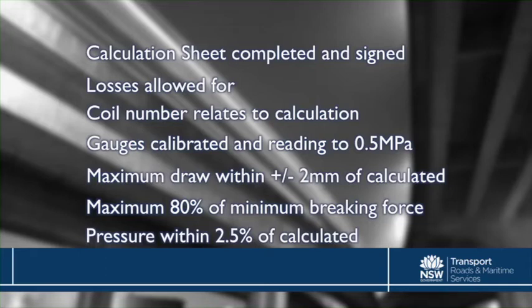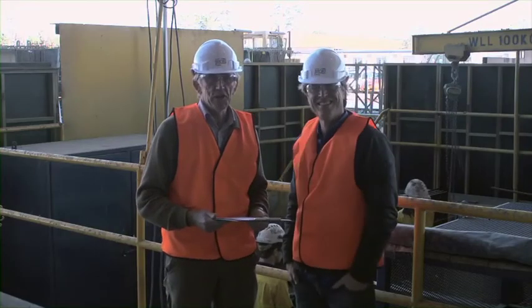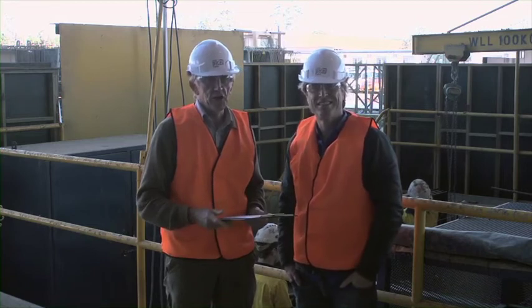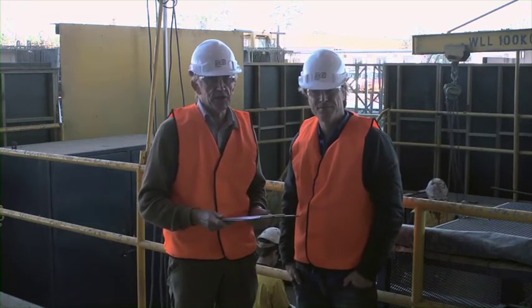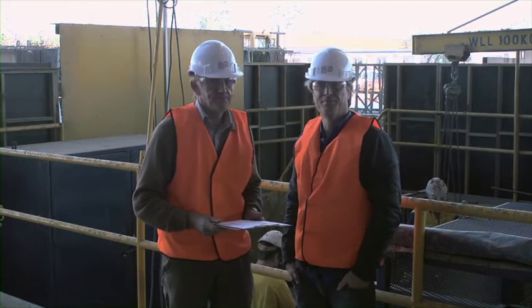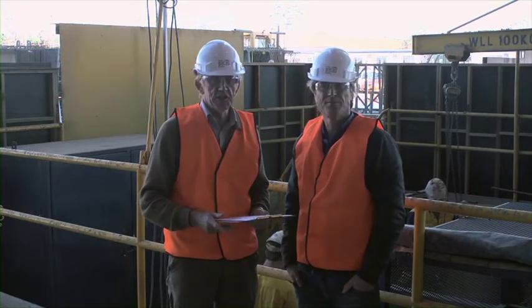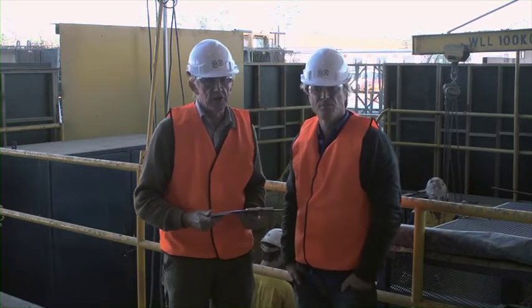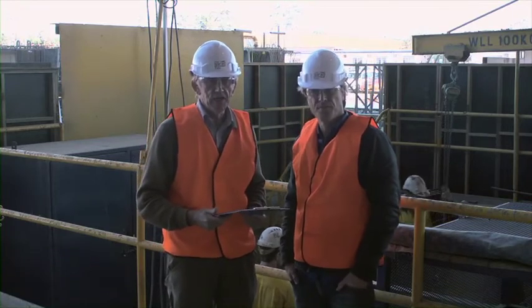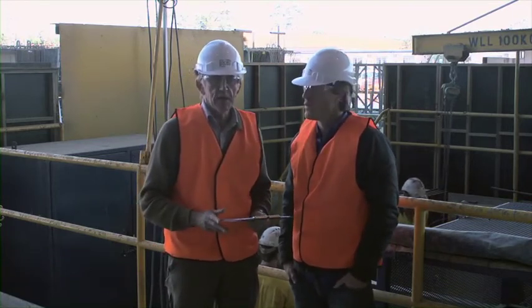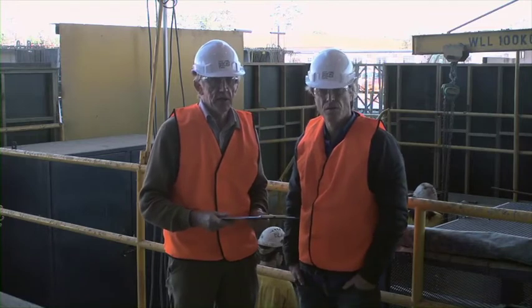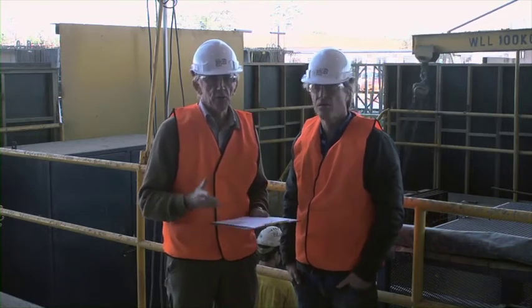That is all well and good if everything is going to plan, but what happens if the actual extension is different from the calculated extension? With pre-tension concrete, this is generally less common, and if it does occur, it's more likely due to a calculation being different to the actual parameters. If the measured extension differs from the calculated extension by more than, say, 3% at any stage, then you should stop the pre-stressing and the cause for the difference determined and take steps in accordance with the relevant specification.